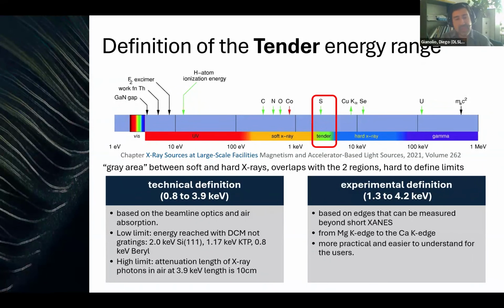While for the high limit, we all agree that normally hard X-ray measurements are done in air, but tender X-ray measurements are normally done in a controlled atmosphere. So the real limitation is how long the path of X-rays in air can be. And so considering a round number that is 10 centimeters, this limit would set the energy around 3.9 keV.